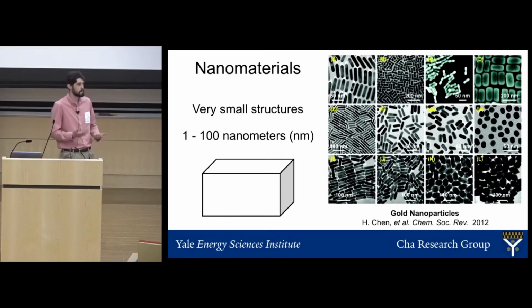And this would continue happening if I kept cutting those blocks in half. I would get smaller pieces of gold that all have the same properties. But when I get down to the length scale of about 1 to 100 nanometers, this ceases to hold, and now the properties of those small blocks of gold will actually change based on their shape and size.